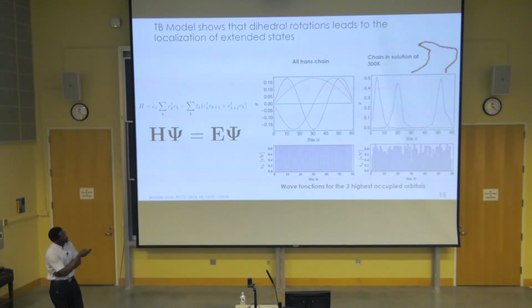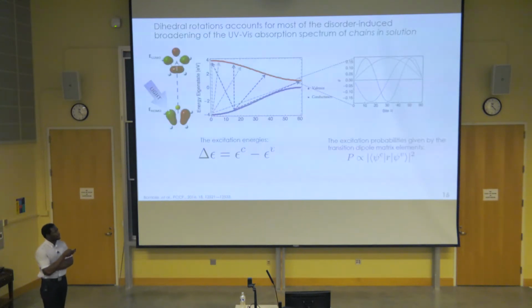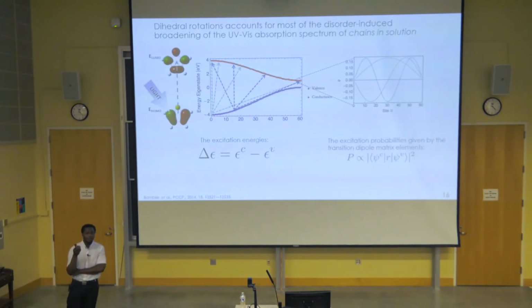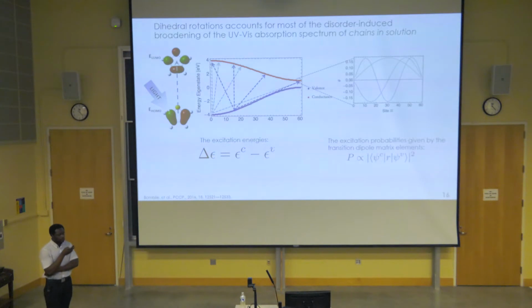And for chains in solution with dihedral disorder, we find that these same states are highly localized. And particularly, we observe that the charge carrier decides to sit in the region of the chain with the highest hopping matrix elements, or in other words, less distortion from planarity. So we went a step further to try to see how dihedral disorder will affect a measurable property. Particularly, we wanted to capture the extent to which dihedral disorder contributes to the broadening of an absorption spectrum.